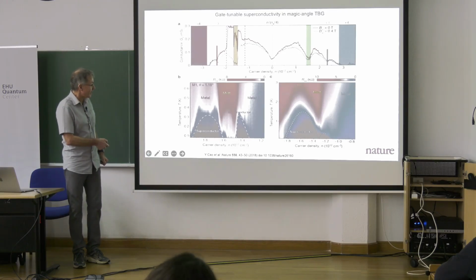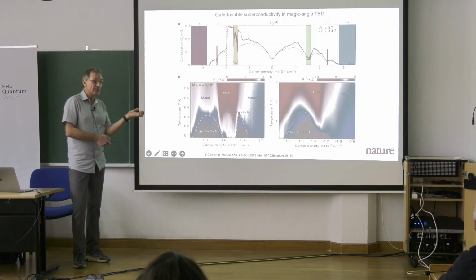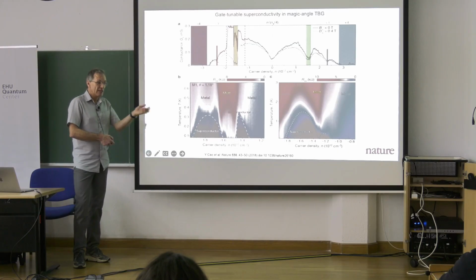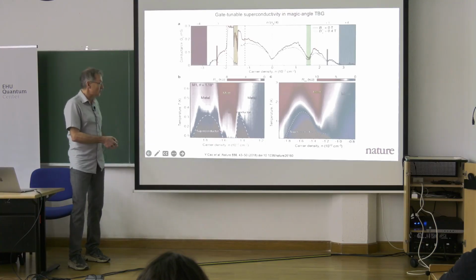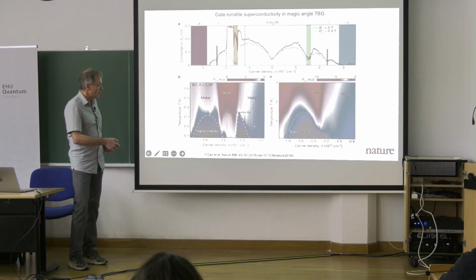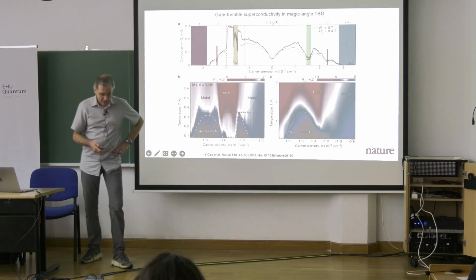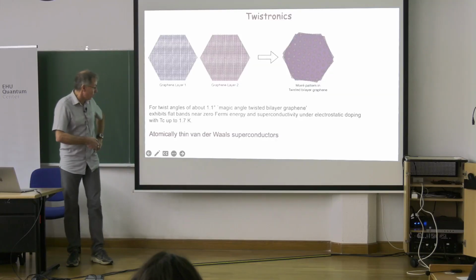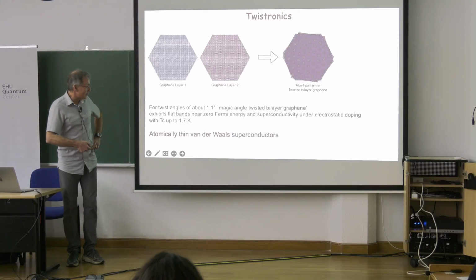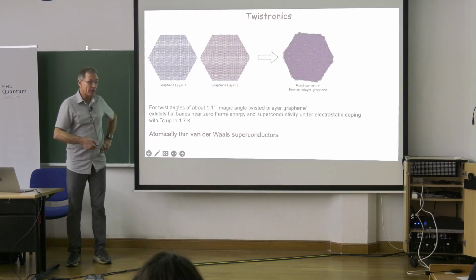So this is a phase diagram, and you do it all in the same sample. You don't take different materials, preparing and so on. You just change the voltage on the device, and you change the carrier density, and you go from superconductor to Mott insulator to another superconductor to metal, and so on and so forth. And this brought this physics of atomically thin van der Waals superconductors.